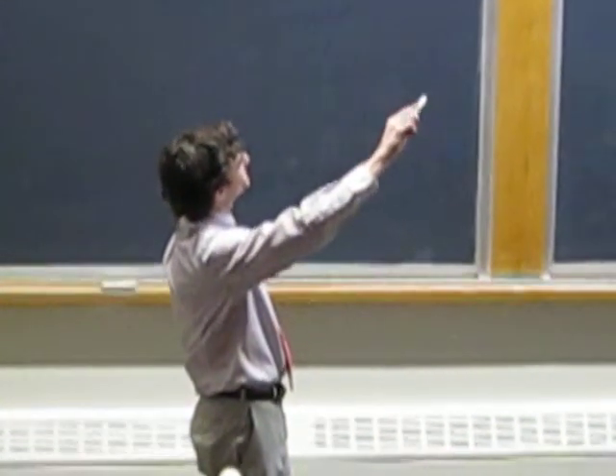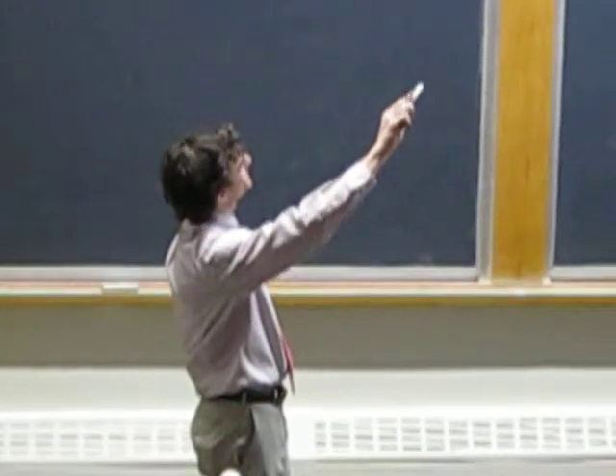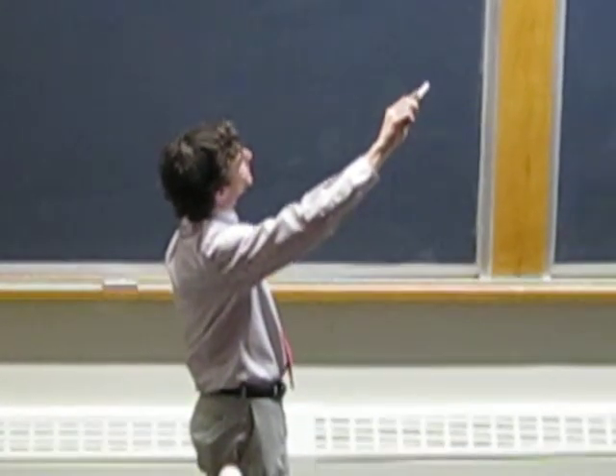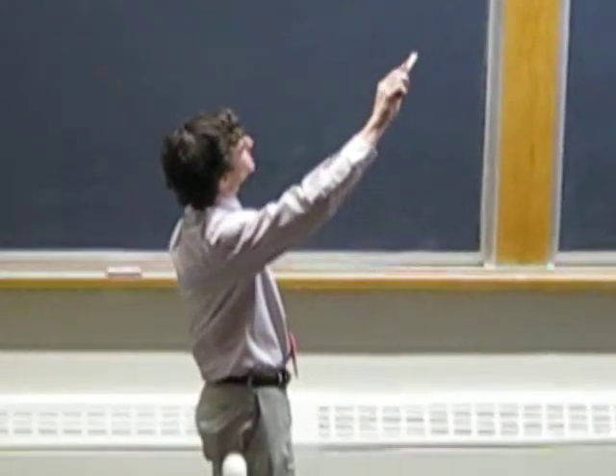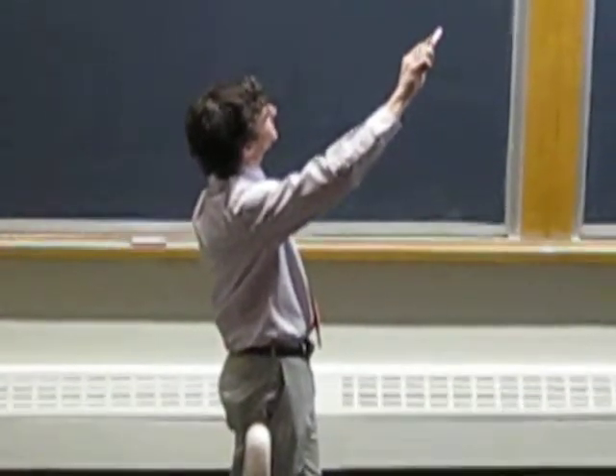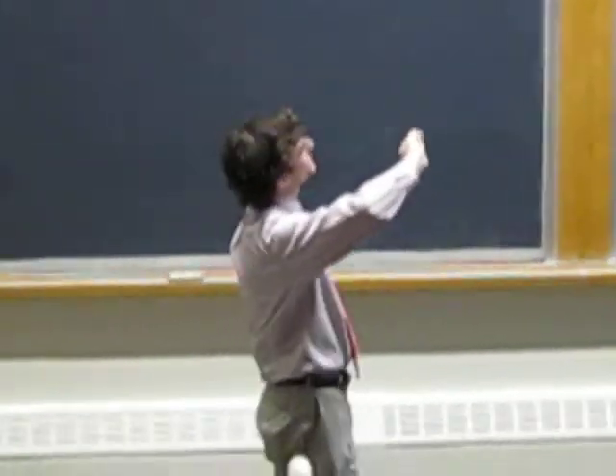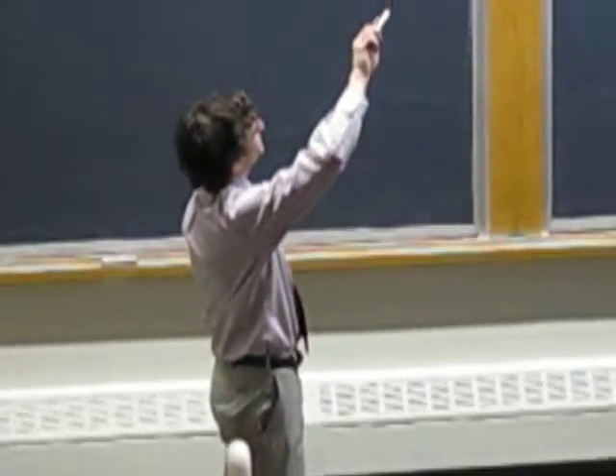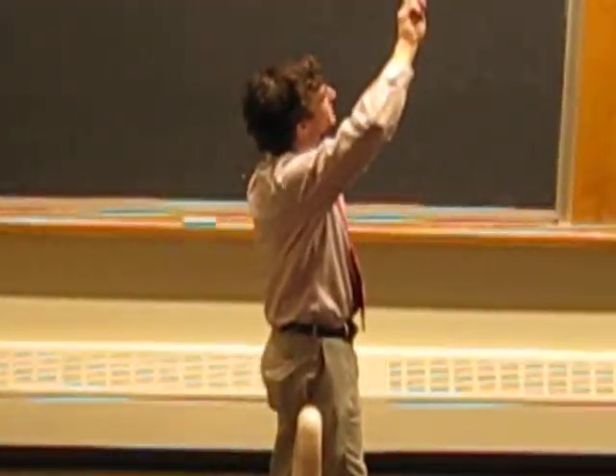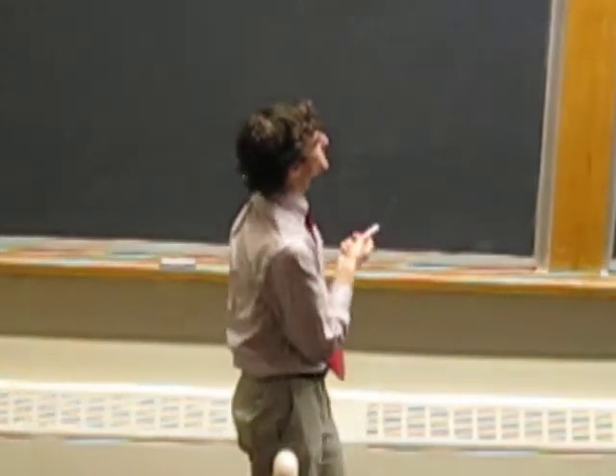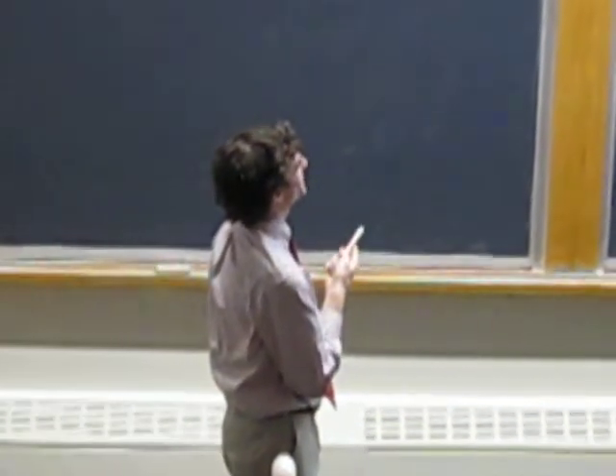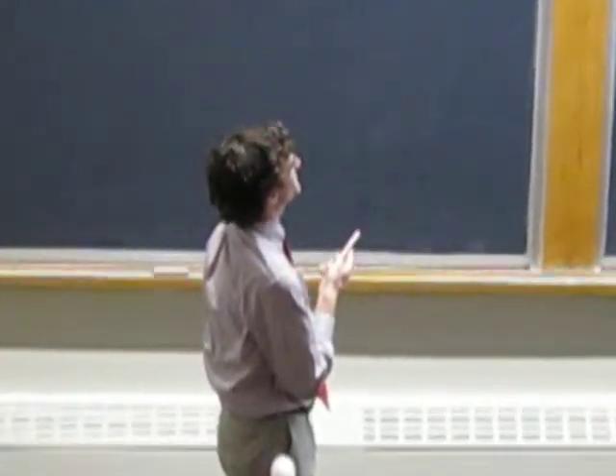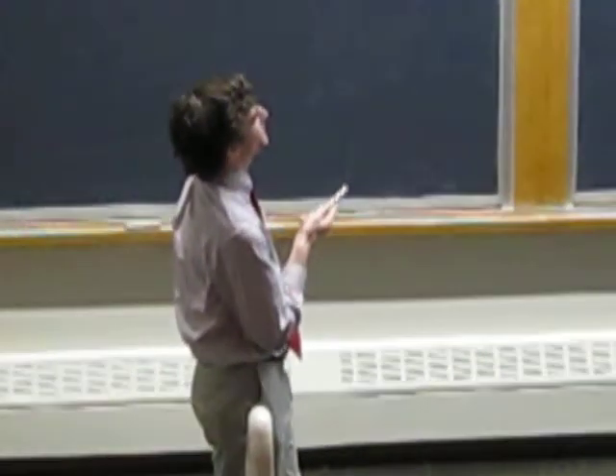So the chi is the red line here, and then the graph without the line is the chi-T plot. So as you lower the temperature, there's no change in the chi-T plot until you reach about 10 Kelvin, and finally you see a turnover in the chi-T. And this is indicative of an antiferromagnetic interaction, but it's very weak because the transition happens at a very, very low temperature. There's no characteristic turnover in the chi versus T plot. So you can model this however you please, actually, because all the models look like this before they have any characteristics. So you can actually fit it to an antiferromagnetic chain,